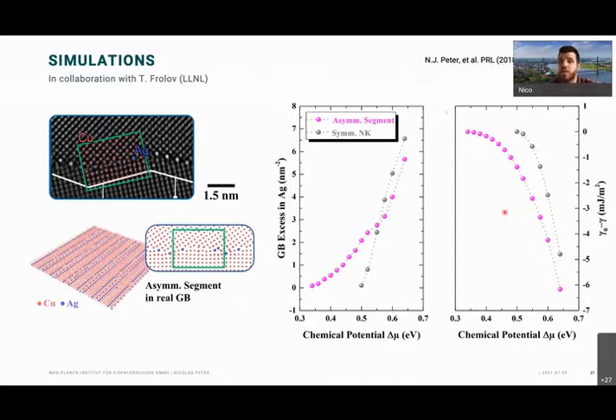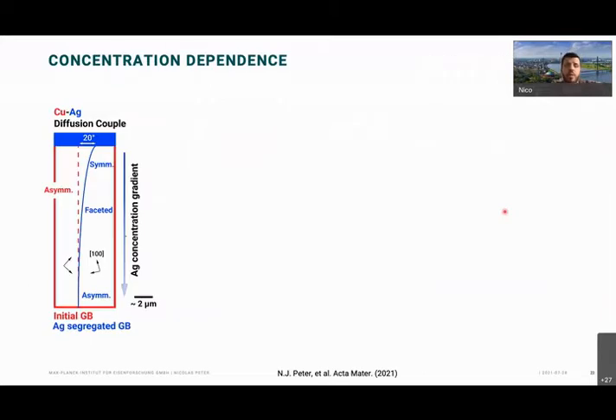Still, there are some questions. For example, why is it not just forming a long line full of silver? And this we try to answer now in a follow-up experiment where we looked at the concentration dependence. What we now did is we took a bicrystal again, with red being the bicrystal and the straight grain boundary running down here. We put silver on top and have it diffuse in under the same conditions as before. And what we see in a cross-section now is that from the surface down into the bulk, the grain boundary moves. So it curves away towards the surface.